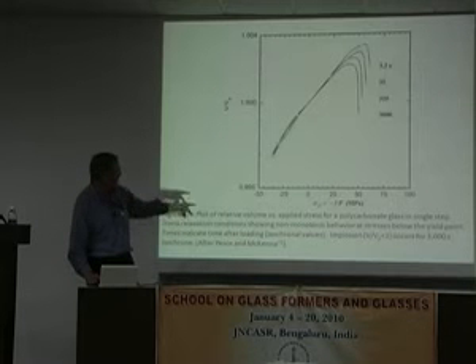I'm accelerating aging. And this just shows what the volume looks like as a function of strain for the material that's showing that funny behavior. And this is actually what we had; another polycarbonate didn't do that at all. This material would yield and flow. This one would rupture. So there's really some subtleties in behavior. And this just shows the volume versus pressure.